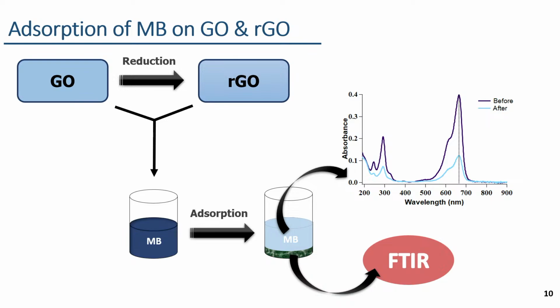And then the methylene blue adsorbed GO and RGO that was suspended at the bottom of this beaker was filtered and further characterized using the FTIR technique, in order to get information about the interactions between methylene blue and these GO and RGO.